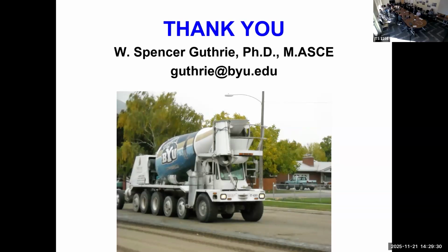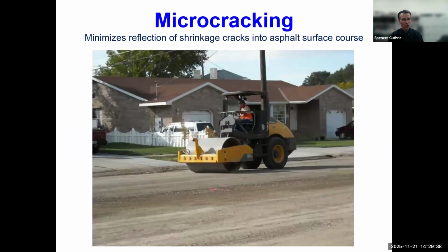Sir, how did you apply the microcracking? Was it by the run of the roller? Yes, as we go back to the picture, I normally recommend a minimum 12-ton roller. Generally, it's the same roller that was used for compaction, and we'll have them do a number of passes over a short distance to establish a roller pattern. We're typically looking between 3 and 5 passes of the roller, sometimes as few as 2, to establish that cracking pattern that we're looking for.